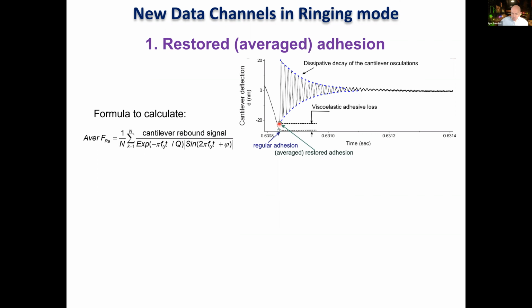We can easily measure the sorption layer without any molecules. When you do calibration on sapphire, for example, you can clearly see that. That's actually one of the things I didn't put here. It's pretty quantitative. We can measure the amount of energy losses on very clean surfaces, and we have that quantified. We have to publish it, but it's there. So it's a pretty accurate calculation. I would say that with 99% certainty, we are speaking about molecules when we measure these energy losses. Right, another question.